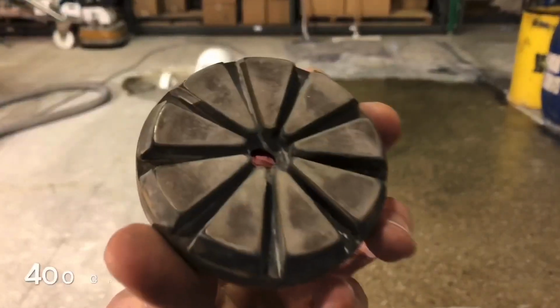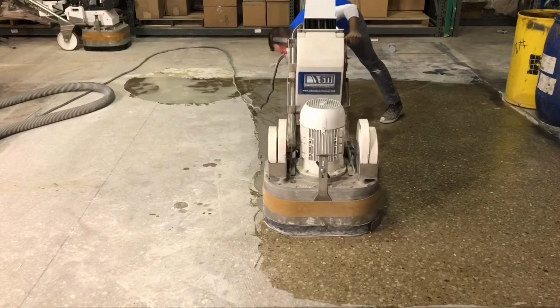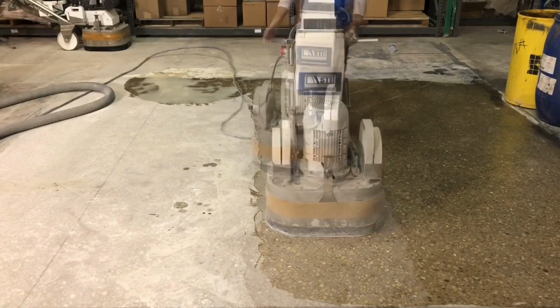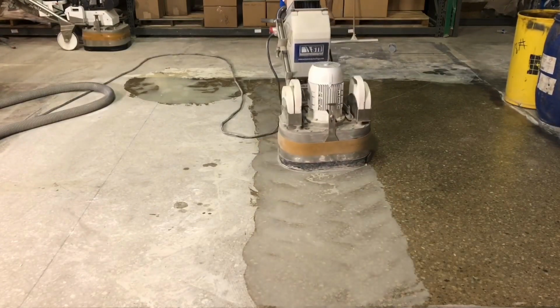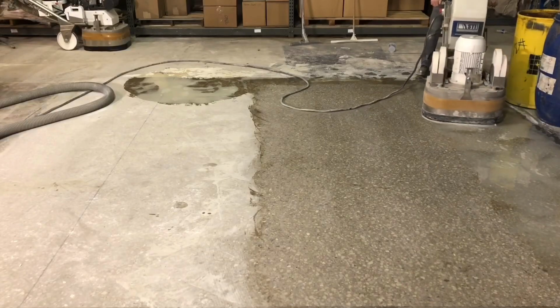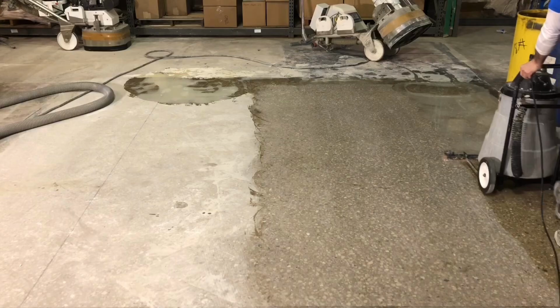Once the urethane was cured enough so it could be cut again, about 90 minutes in this case, a 400 grit rubber back tool was used to take off the overfill. This step was also done wet so that the friction from the tool wouldn't pull the urethane back out of the holes. Same as with the epoxy. The goals of the 400 rubber back is to remove the overfill of the urethane and then also to process the floor to remove the 200 grit scratch.